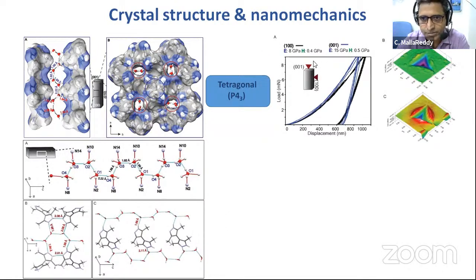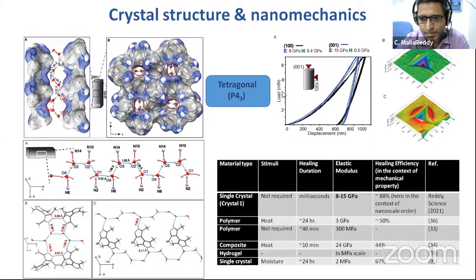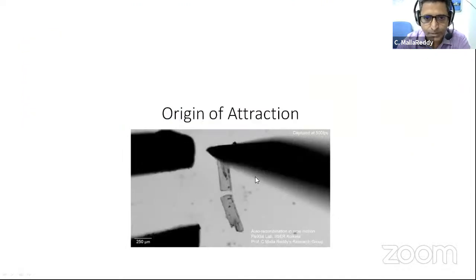And we did nanoindentation to see how hard or stiff these materials are, and compared them to many other materials. So these are very stiff, and healing is also very, very fast. In most cases, healing takes hours, or 2 minutes at least, and most of the time you require either heating or a catalyst or something else like moisture or some other stimuli. So it is very rare to have a hard or stiff material which heals very fast, with no external direction, and also there is no diffusion here. So it is a totally different mechanism. That is what makes this mechanism very unique compared to most other materials.